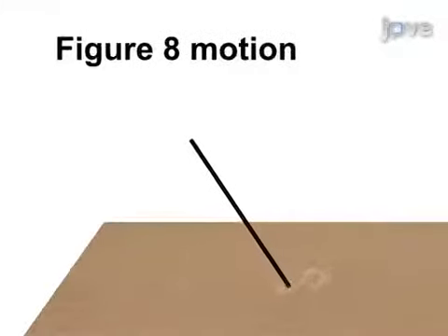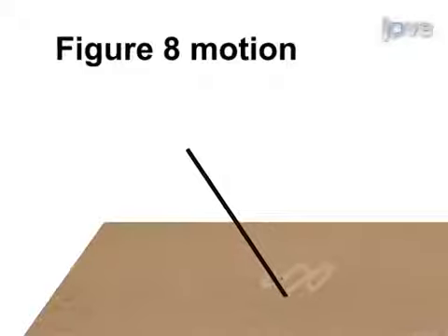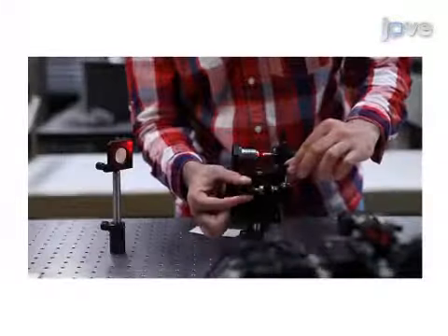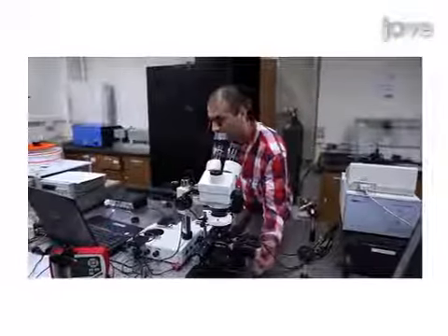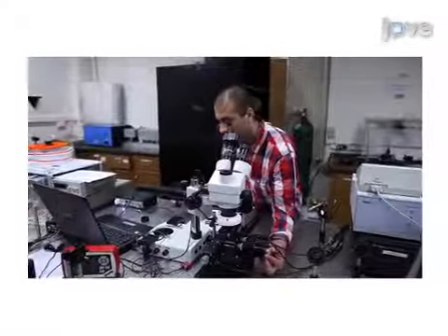Next, the samples of drawn fiber are cleaved and polished for the optical characterization of Anderson localization. The final step is to test the samples in the optical setup by illuminating the disordered fiber with helium-neon laser light. Ultimately, the output intensity profile of the localized beam is imaged on a CCD camera beam profiler to show the transverse Anderson localization of light.